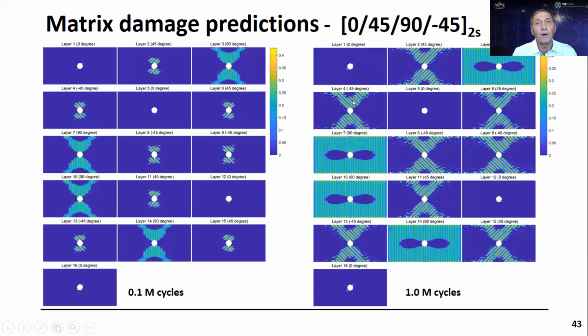And here I'm showing you for the quasi-isotropic laminate, after 100,000 cycles and 1 million cycles, in the 0 degree plies, pretty much there is no matrix damage. And in the 90 degree plies, there's of course an extensive amount of damage that you see. And in the 45 degree plies, you see the pattern is along the fiber direction. And of course, as expected, after 1 million cycles, the damage is substantial.